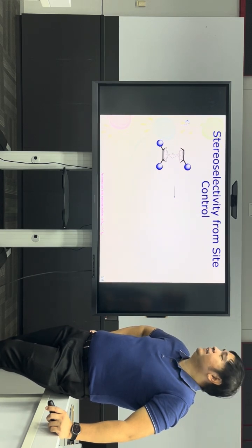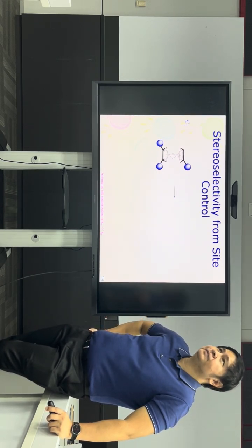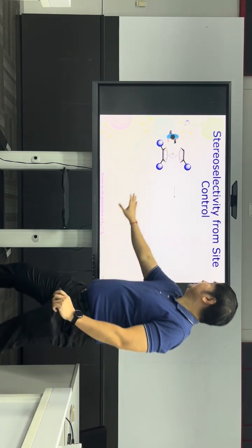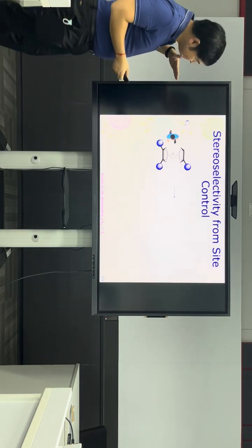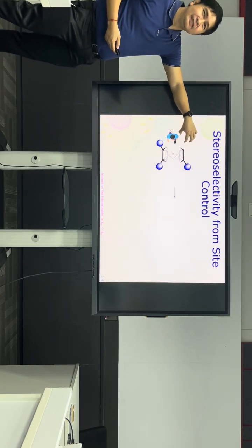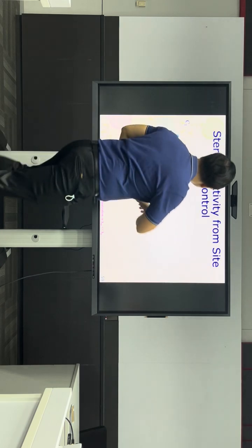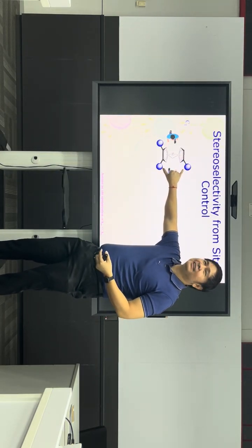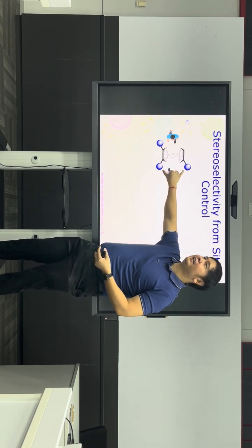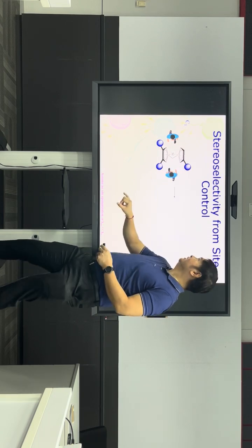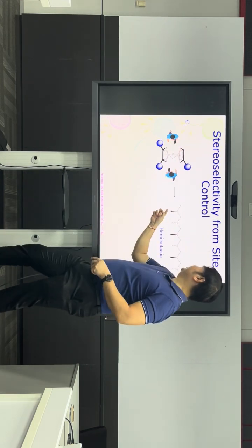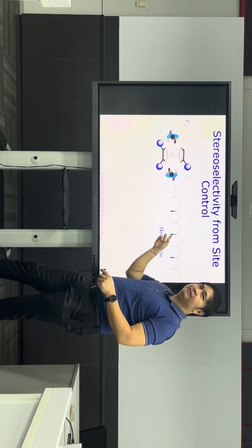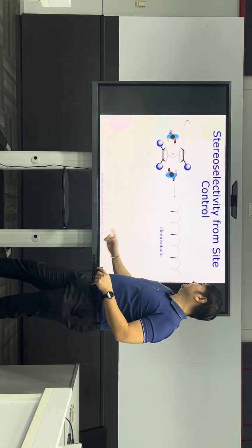Now what about something that looks like this, C1? How can we identify this? If you go from this side, what happens? Left side is good, right? If you approach on this side, what happens? It's the same, right? Left and right here, see, it's the same. So it can be random. That means on one side it's up. The next one is random. Next one is up. Next one is random. Hemi-isotactic.